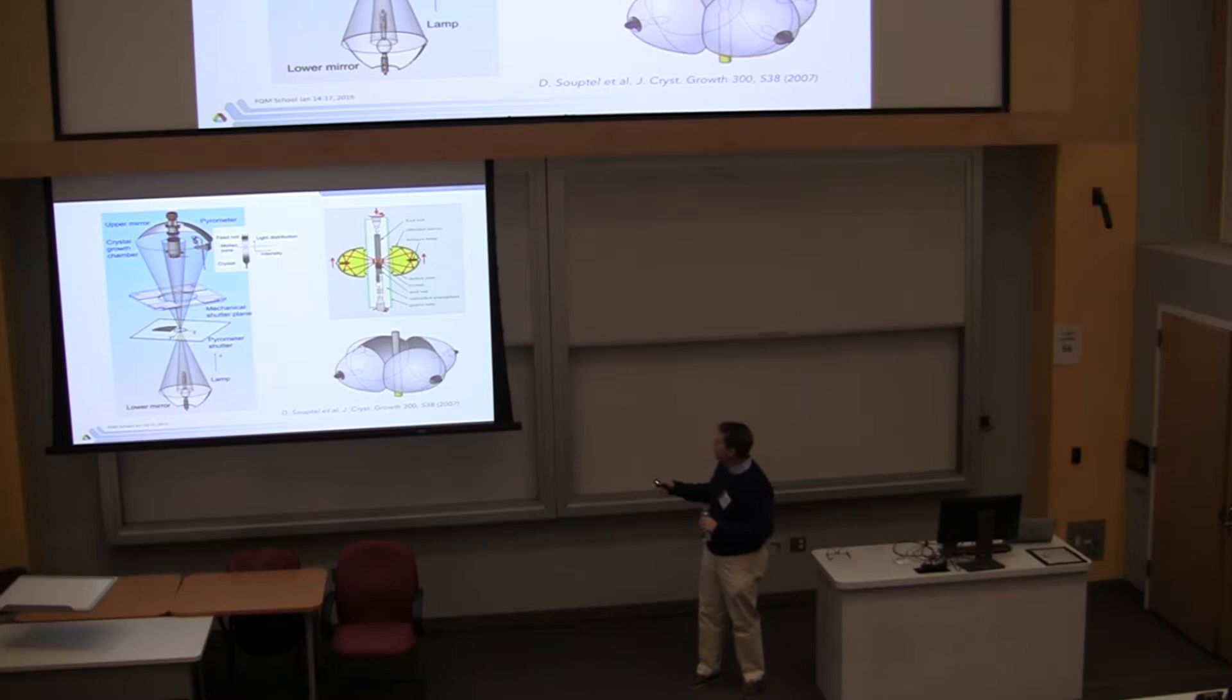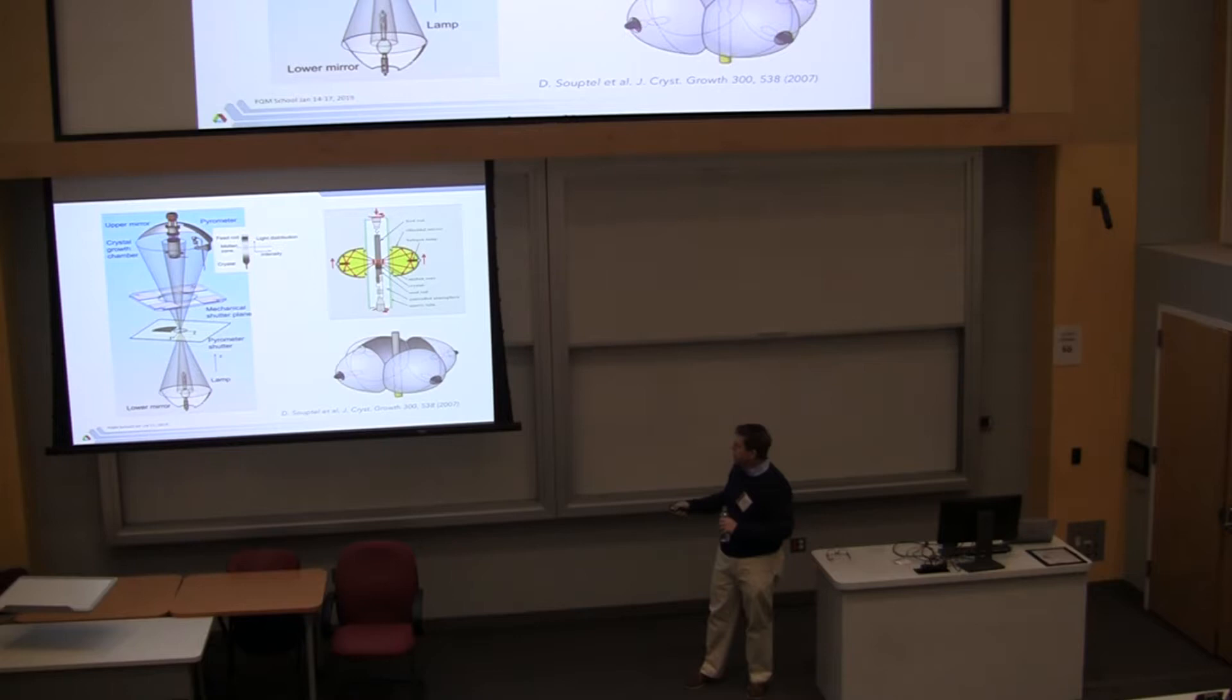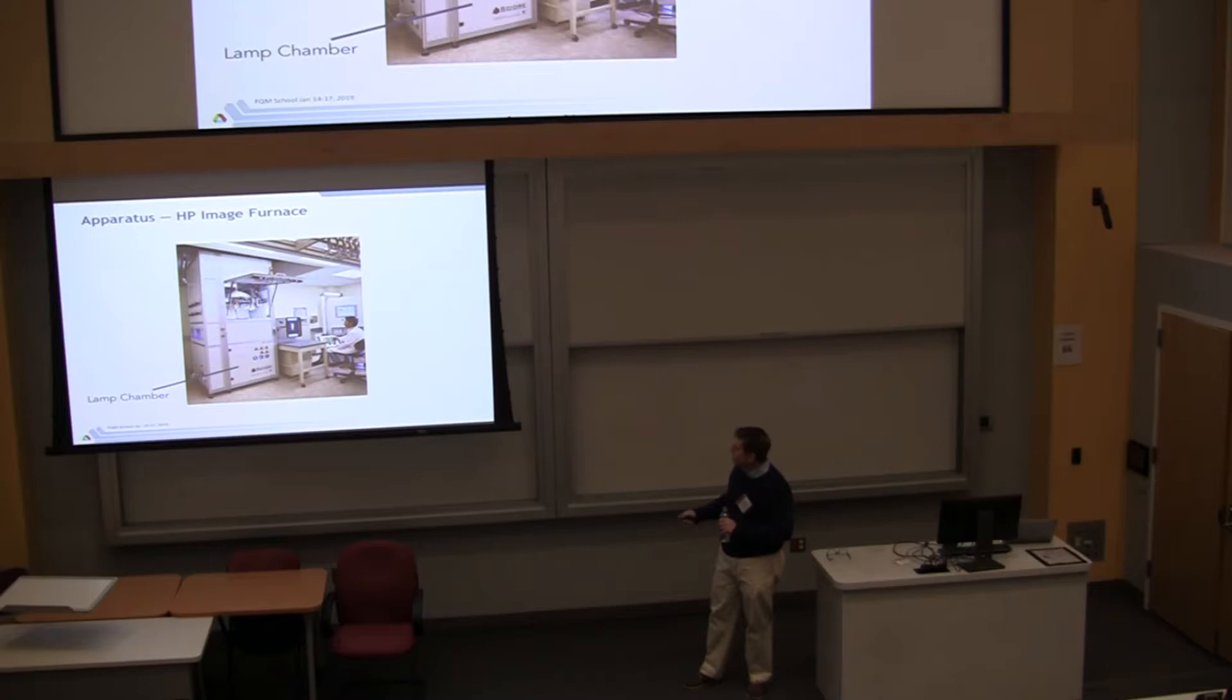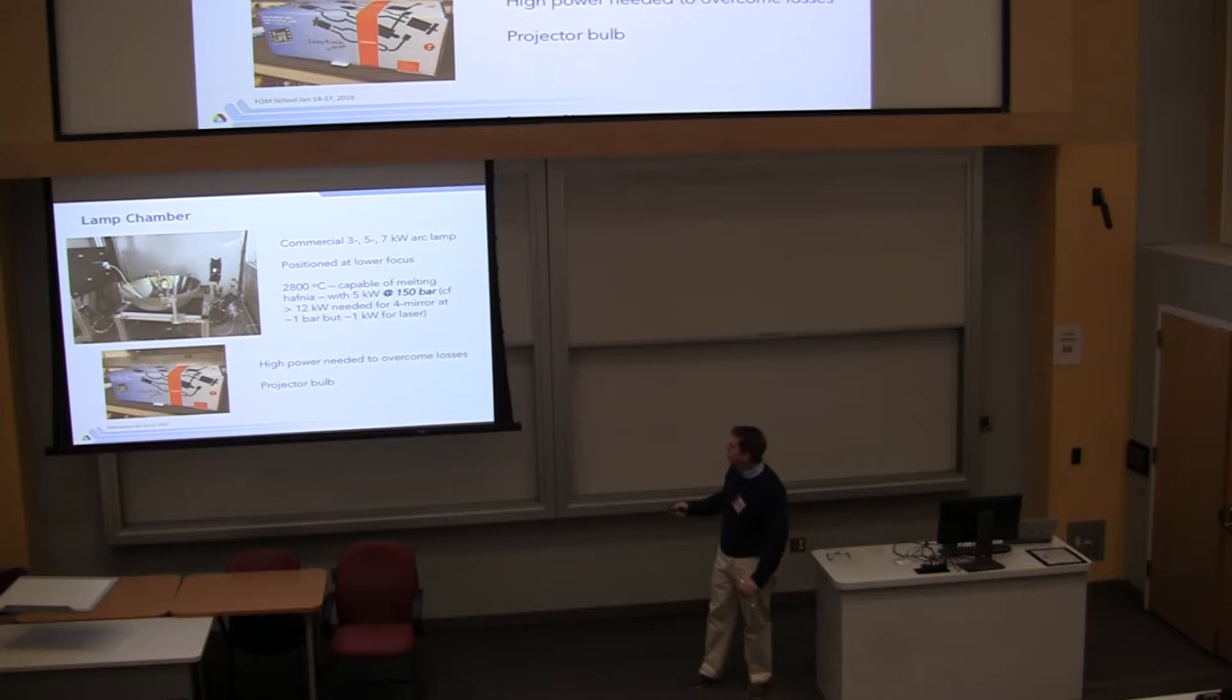And the fact that this line has a given slope of minus one quarter is relevant because it says that there's a law of mass action that's associated with this process of dissociating or removing oxygen from VO2. And you can actually write an equilibrium constant. So you can actually see that there's thermodynamics going along here. So what's the impact of this if you want to grow a crystal? So if you want to grow a crystal, here's copper oxide.